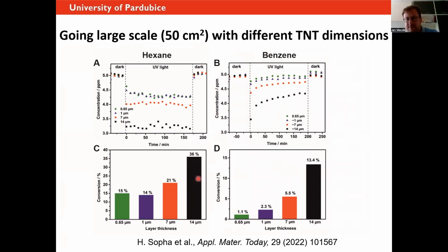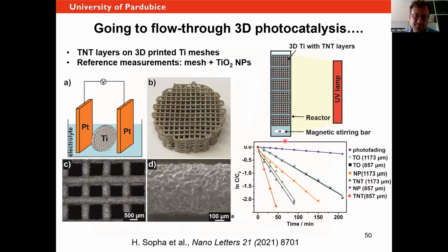So this clearly shows us that if we would be able to make these layers even thicker, we would probably have ultimately good unbeatable conversions of these gases. And this all also in relatively short time. So please understand that this is a very standardized experiment done really following some ISO norm. You have to give it some time to saturate it and so on. So these are really good and consistent data that show how the tube thickness influences the photocatalysis, and we are trying to understand this in more details.